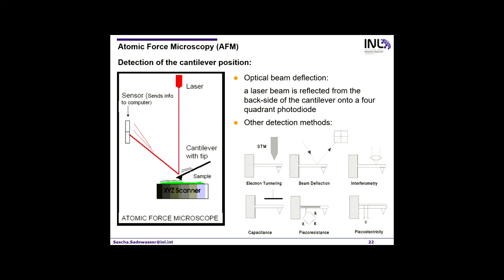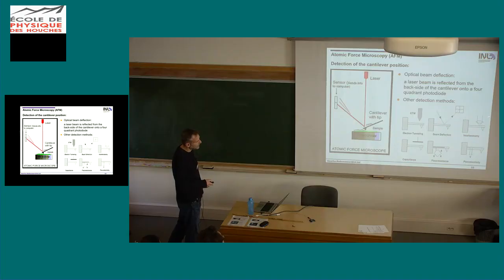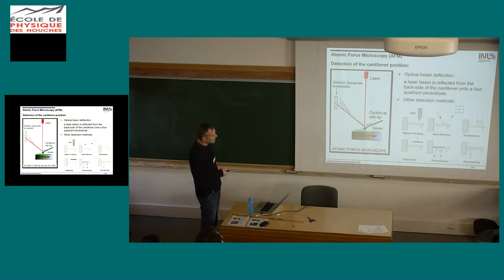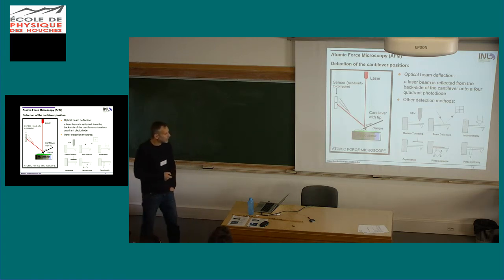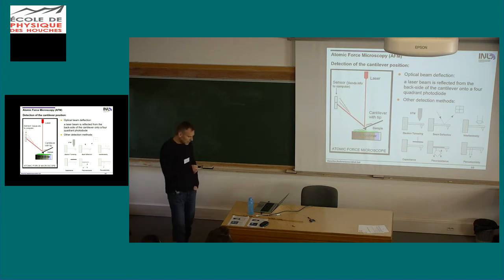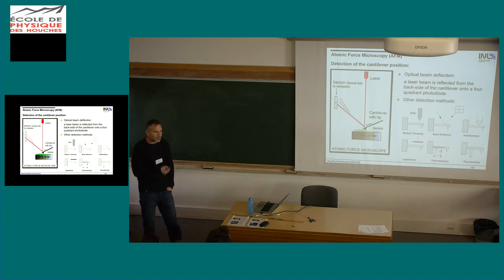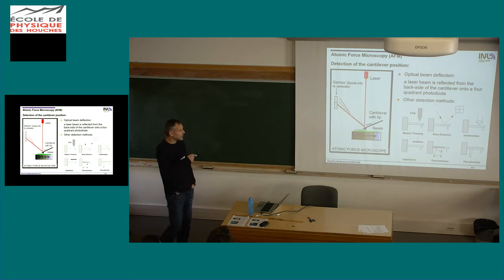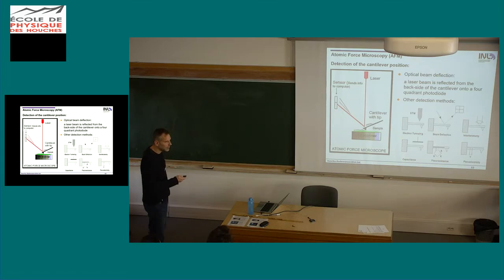But there are also other detection modes. We saw this one already. This is the beam deflection. There's interferometry. You can do capacitance, you can do piezoresistive or piezoelectric. And more recently, the piezoelectric one is becoming quite popular because you don't need an optical system and you can get very high precision measurements. This is the so-called qPlus sensor where a quartz is used, and they measure oscillations of the cantilever of 5 picometers. So very small movements.